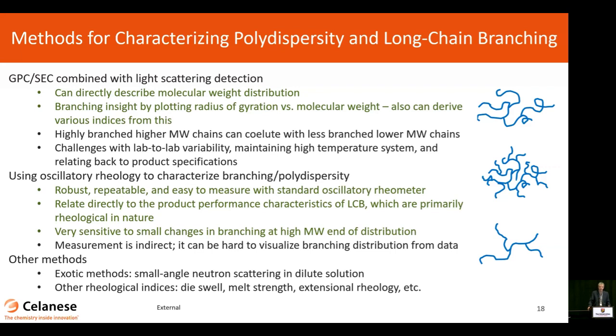The downside of this method, there's a couple. One is that highly branched, high molecular weight polymers can co-elute in a size exclusion chromatography experiment with other less branched, lower molecular weight copolymers, just because this separation method is primarily due to hydrodynamic volume. The other thing is that these instruments can be challenging to maintain, and lab-to-lab reproducibility is not typically very easy to achieve.